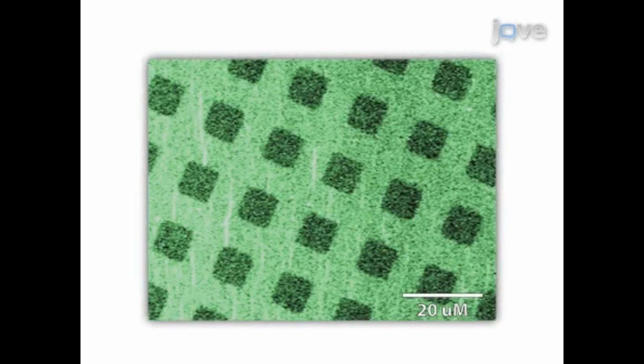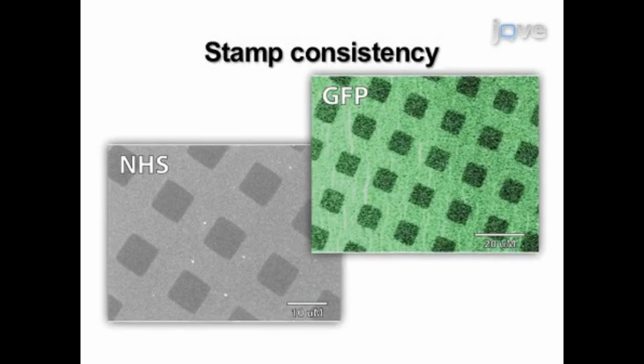Under fluorescence microscopy, there was a clear intensity difference between GFP-modified and hydrolyzed free carboxylic acid regions. The size and shape of the replicated features are consistent between both NHS patterned and GFP-modified surfaces, confirming the remarkable stability of carbon passivated surfaces and the selectivity of the stamping approach.